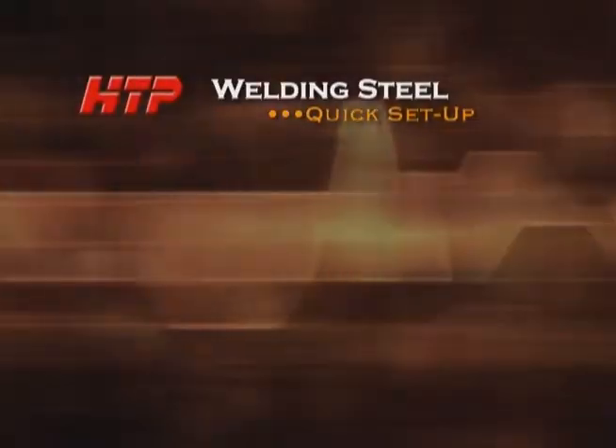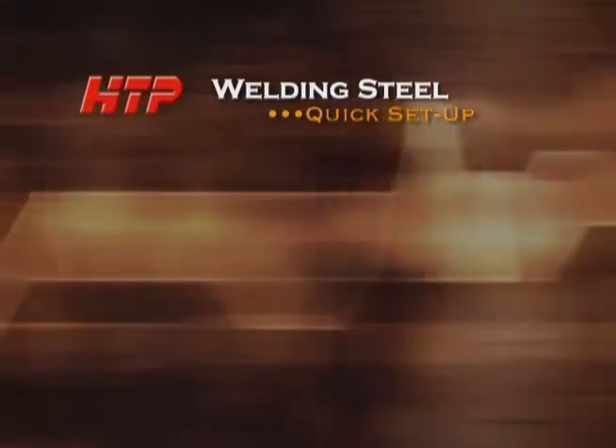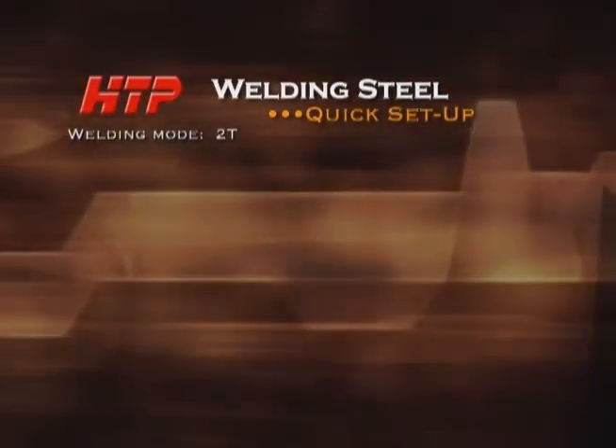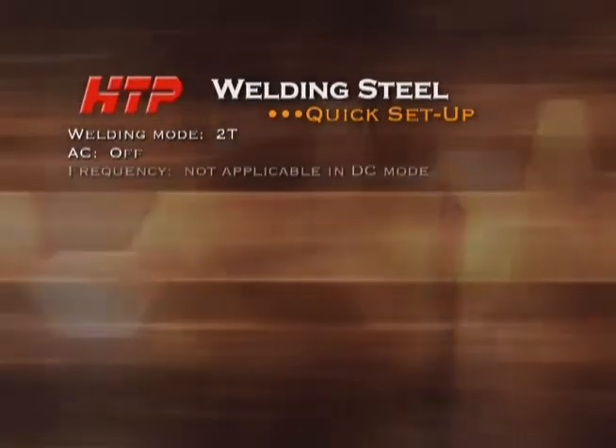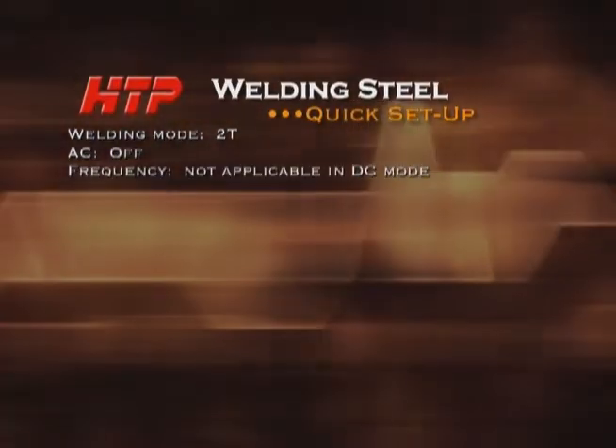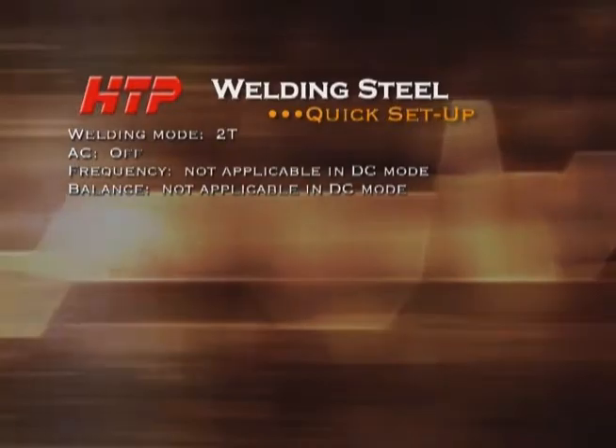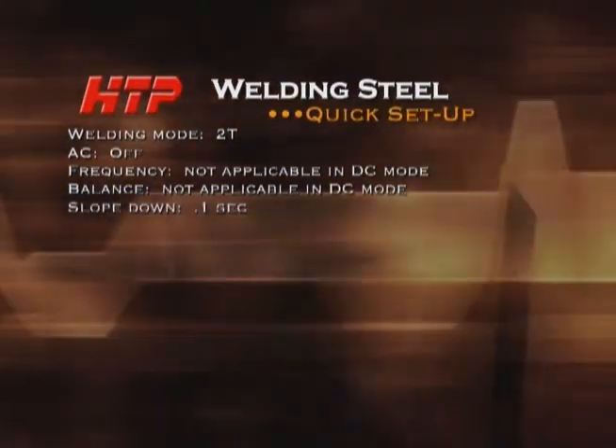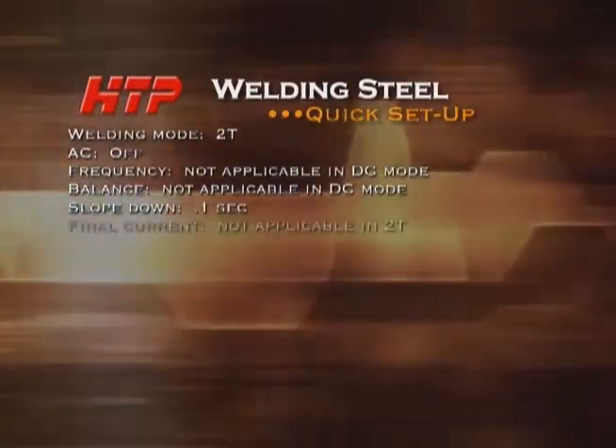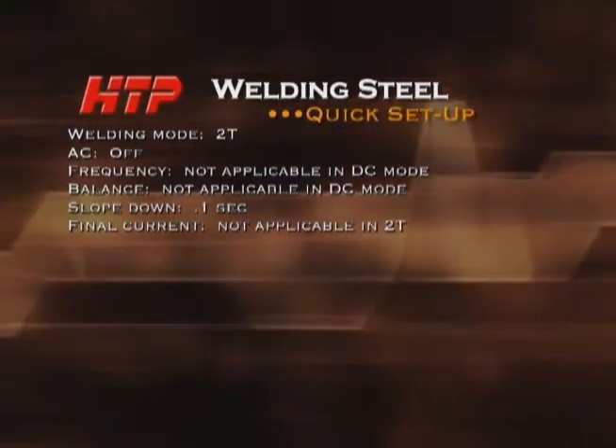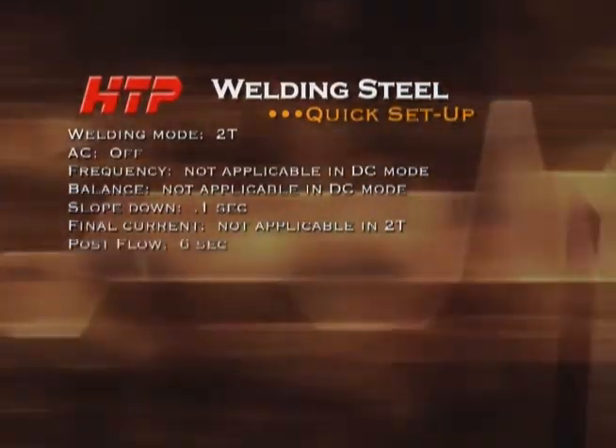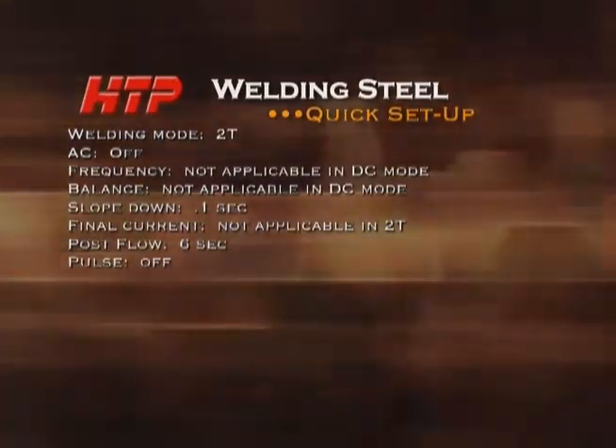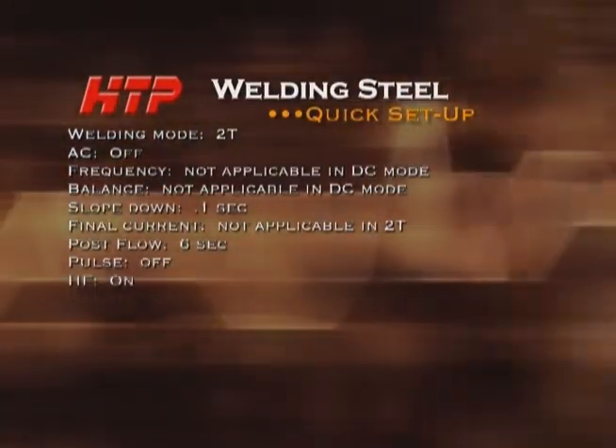Welding steel. Once again, we are going to give you the basics for machine setup. 2T mode. AC off. Frequency not applicable in DC. Balance not applicable in DC. Slope down 1/10 of a second. Final current not applicable in the 2T mode. Post flow 6 seconds. Pulse off. HF on. Remote on.